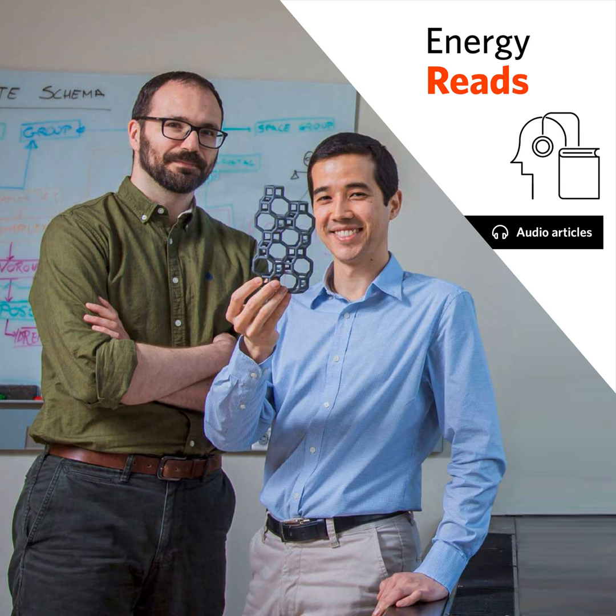Using a literature mining technique that she and a group of collaborators had developed, she and her DMSE team processed more than 2 million material science papers, found some 90,000 relating to zeolites, and extracted 1,338 of them for further analysis. The yield was 549 templating molecules tested, 209 zeolite frameworks produced, and 5,663 synthesis routes followed.